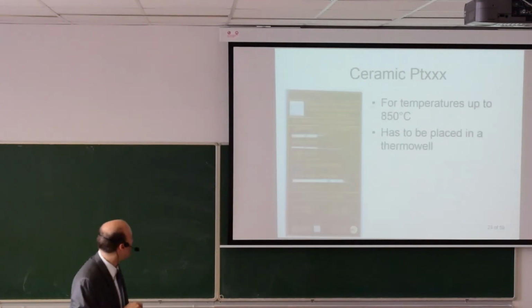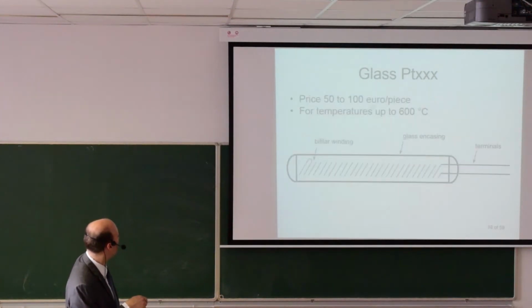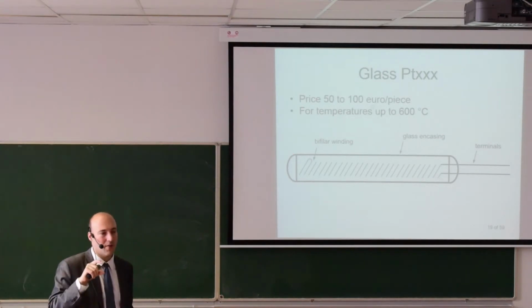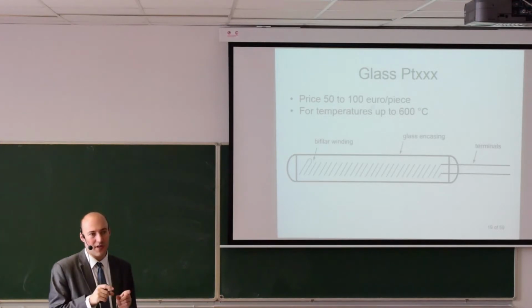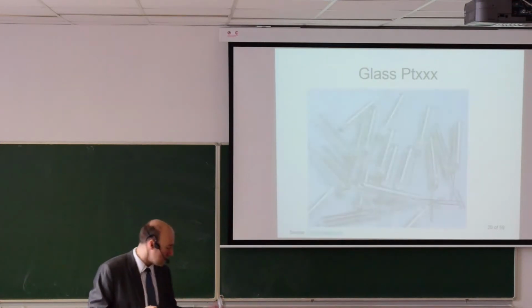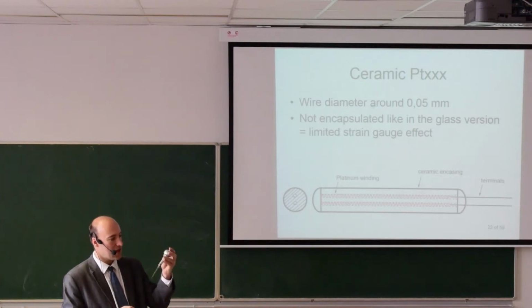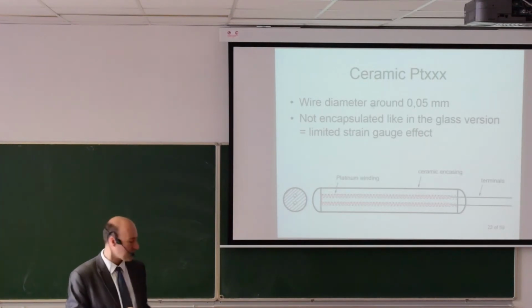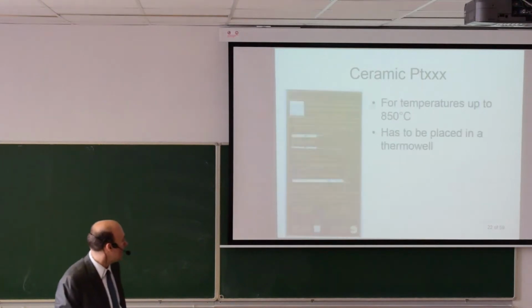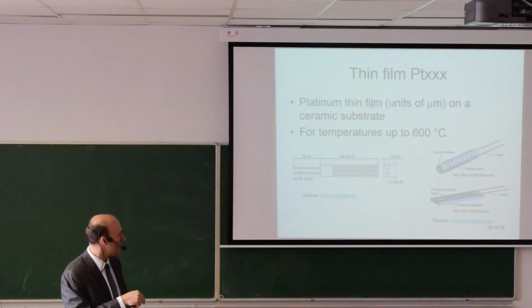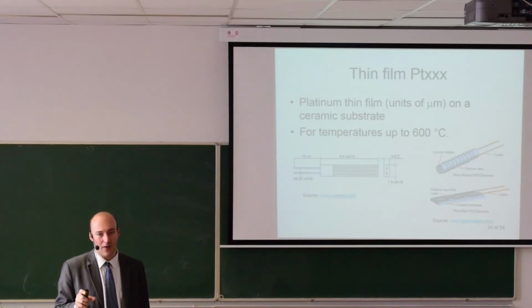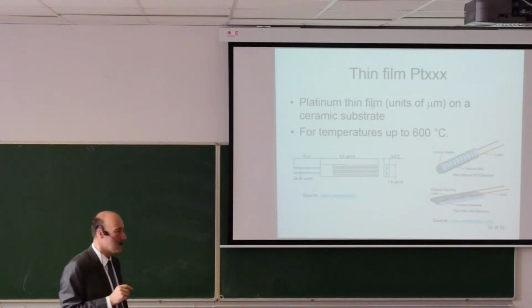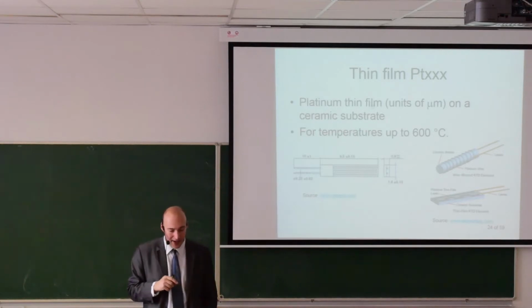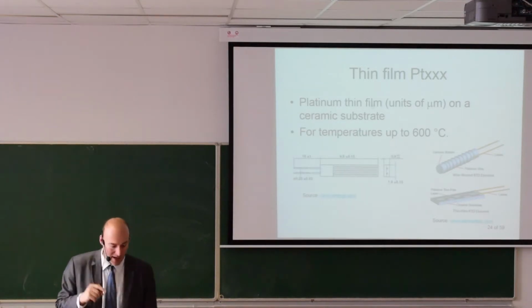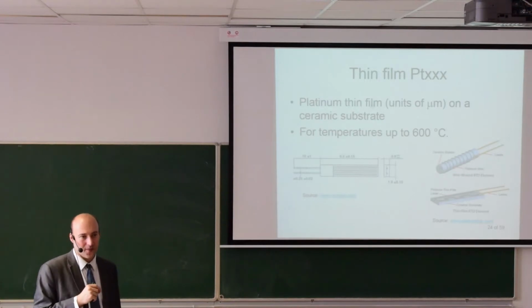I forgot to mention it here, but it was not written here. Yeah, a glass PT100, just the sensor itself, is somewhere between 50 and 100 euros per piece. So the sensor like this can be, let's say, 3,000 Czech crowns, roughly. On the other hand, the thin film sensor will be like 100 Czech crowns. So it's about 10 times or maybe 30 times less expensive than the other sensors. But it's also less accurate.